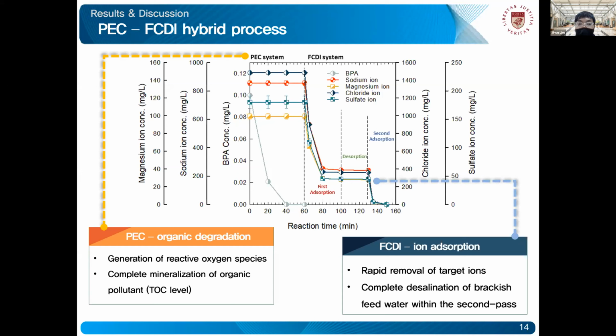And through this analysis, we confirmed the feasibility of the PEC-FCDI hybrid process for producing an organic-free permeate that satisfies freshwater TDS concentration. Also, the operation was conducted in the long term, and we found that the stability of both the PEC system and the FCDI system was maintained almost evenly throughout a 24-hour period.